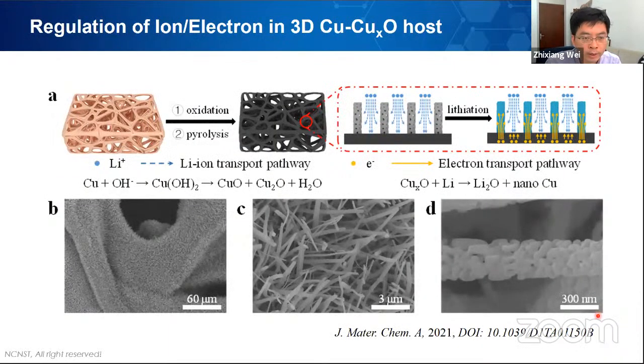Recently, not only for the organic structures, we are also extending these structures to inorganic ones. For example, recently we used copper foam to make a three-dimensional copper oxide material, using this substrate to grow copper oxide nanowires. These nanowires can regulate the ion and electron transport pathways, and therefore you can get a really good material for lithium metal electrodes.